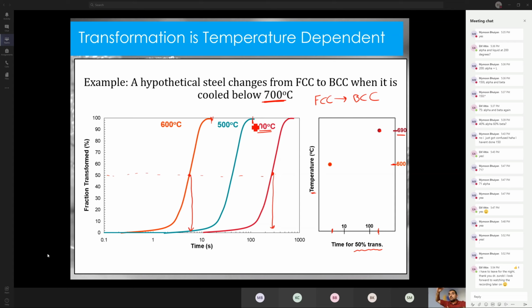FCC is only supposed to be there above 700 degrees. So now I'm a full 200 degrees below that. That FCC should be gone. But the reason it's taking a long time to go away is that the diffusion is very slow. It's taking a lot of time.